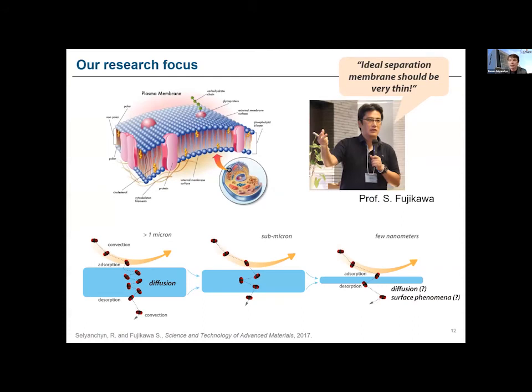And why is thinning an interesting approach? It is a necessary approach, as we saw from the cost perspective: we critically need to increase how quickly gas passes through the membranes. We critically need to increase the permeances of CO2 in the membranes. And taking inspiration from nature, which has already constructed ideal and very selective and very quick membranes, namely cell membranes as shown here, we investigate membranes with extremely small thicknesses, moving from conventional thicknesses around 1 micron and sub-micron to the sub-100 nanometer range.